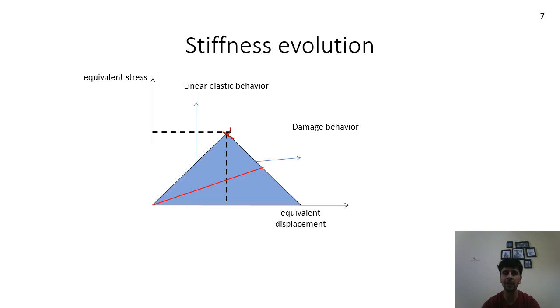After damage, the value of the modulus can be reduced using curves like this. So the modulus initially was this, but now my modulus after damage is this. And you have 4 such curves: longitudinal tension, longitudinal compression, transverse tension, and transverse compression. Based on the modulus variation, you can calculate the value of the different damage parameters.